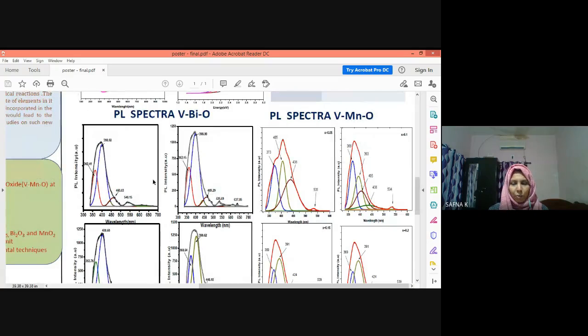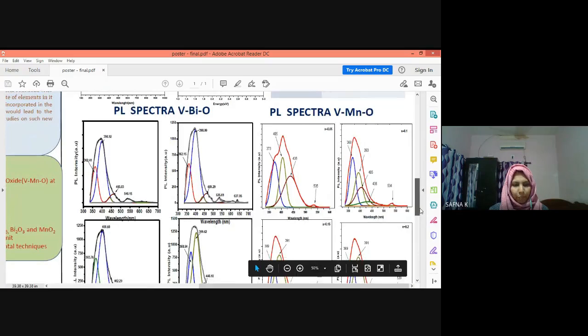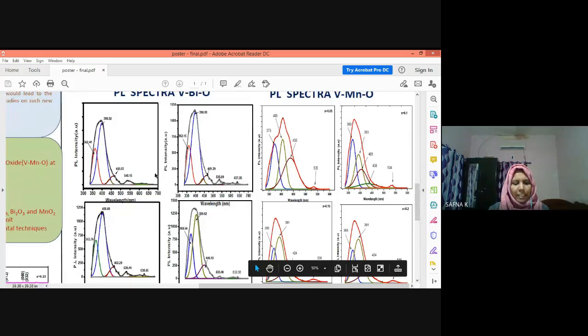This is for bismuth and this is for manganese. Major emissions were observed around 370 nanometers, 390 nanometers, 400 nanometers, 460 nanometers, and 535 nanometers. The emissions have been mostly attributed to the radiative transition between electron-hole recombination.